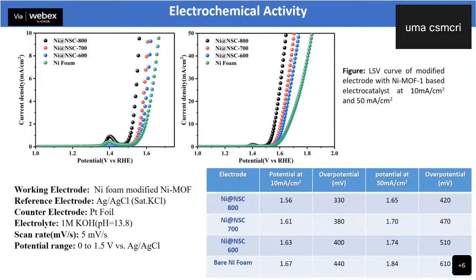In OER, we found that the nickel 800 materials have good electrocatalytic activity. The 330 millivolt potential is required to achieve 10 milliampere current density. And while we talk about the 50 milliampere current density, then 420 millivolt potential is required. So nickel 800 materials have good electrocatalytic activity as compared to nickel 700 and 600.